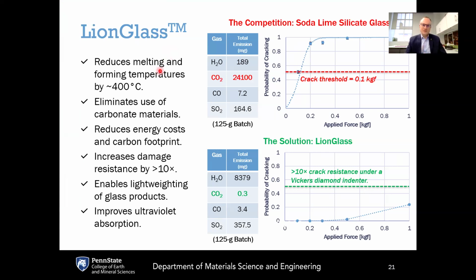And this, first of all, reduces the melting temperatures by about 400 degrees Celsius compared to standard soda lime silicate. It also eliminates the use of carbonate batch materials. And so, for example, the table here on the top shows the measured amount of gases that are released during the batch to melt conversion process for a 125-gram batch of soda lime. And that leads to over 24 grams of CO2 being emitted just as a result of the carbonate batch materials.